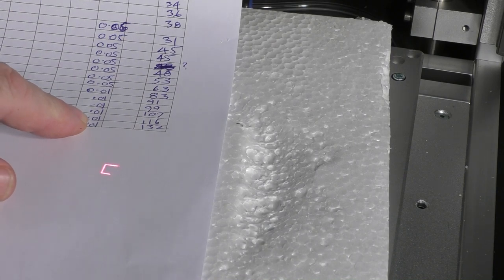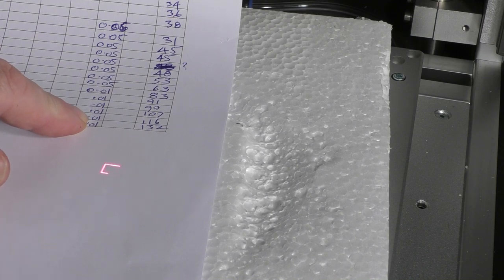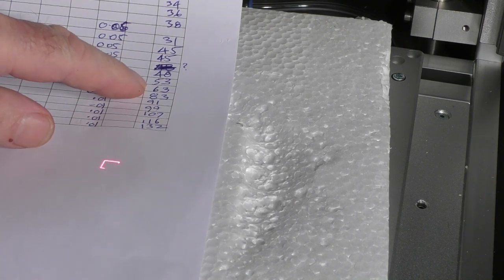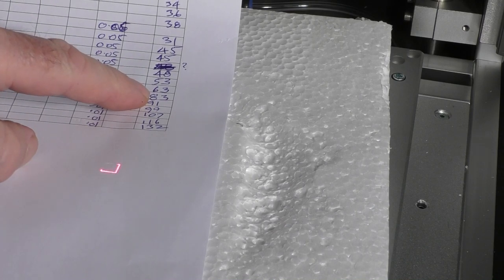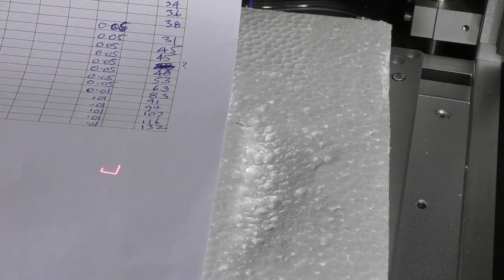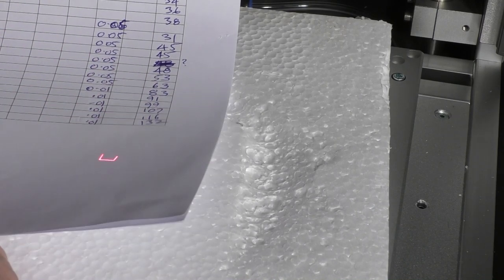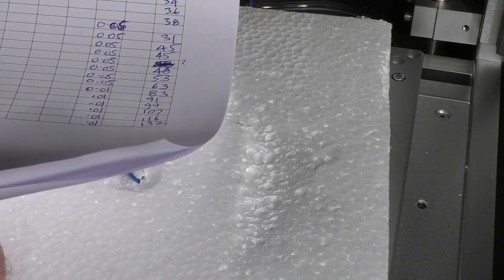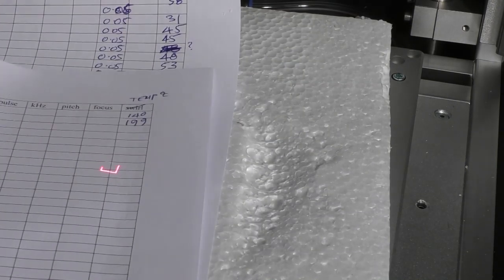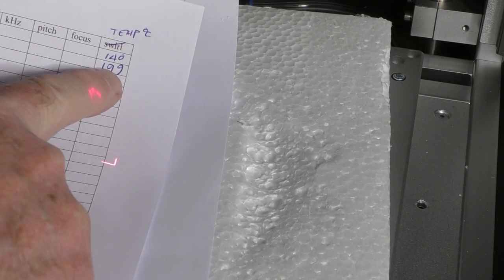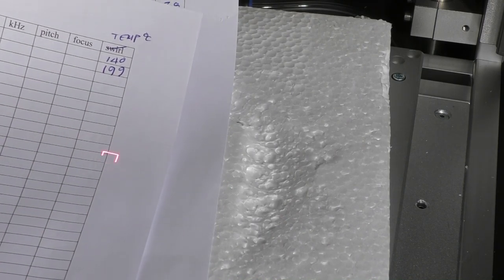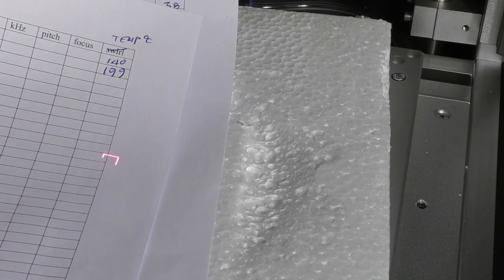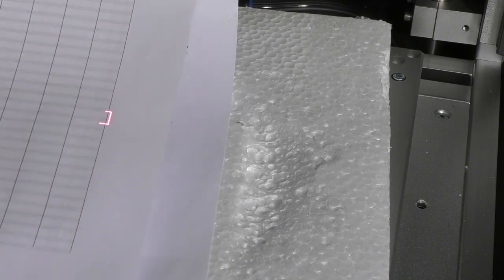So at the moment I'm not producing huge temperatures. You can see they're 31, 36, 38, 48. When I get to this latter set here which was 0.01, in other words the spacing between the lines was very close so I was overwriting several times the same spot almost, then the temperature started to go up. It was 83 up to 132, and by the time we finished the test at 200 millimeters a second we're up to 199 degrees C, and you think oh 199, I should get a little bit of color there, I'm sure.